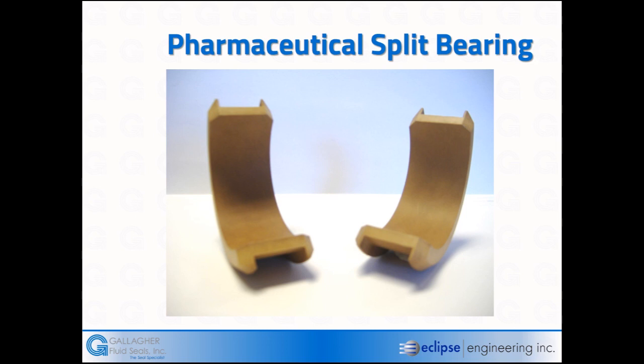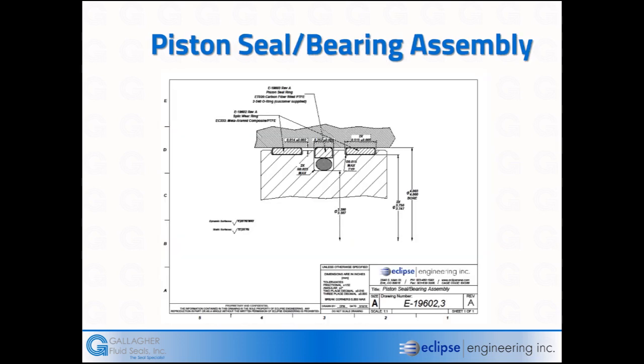We came back and replaced it with a polyimide-filled PTFE split bearing. We solved the wear on the shaft, and even though the loading of the Teflon element didn't handle nearly as well as the PEEK, in this particular application, the PTFE elements were more than sufficient to take care of the load at a lower cost to the customer without having to replace an 8-foot-long stainless steel shaft. So materials are very, very important.